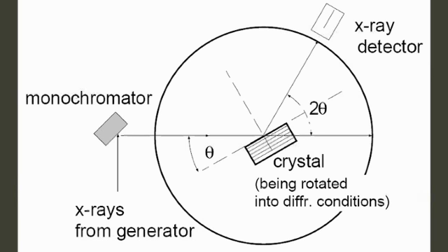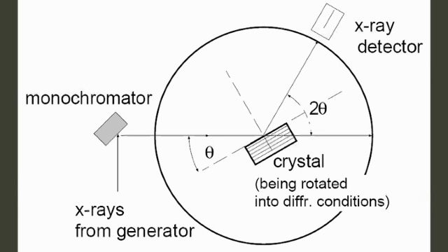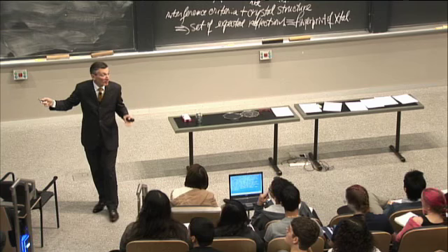And coming out of the collimator is the monochromatic beam. We want single wavelength. So this is collimator, means it's monochromatic and coherent. So that beam comes and strikes the specimen. And for historical reasons, instead of calling this the angle of incidence and this the angle of reflection, they call the angle that goes to the detector 2 theta. In other words, the projection of the beam. This is theta incident equals theta r, so this is really 2 theta incident, or it's 2 theta reflected. It's the same thing.